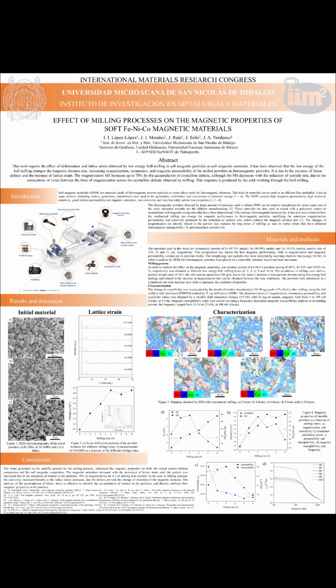Regarding the materials and methods, we used commercial powders of iron, nickel, and cobalt with high purity and particle sizes around 130, 10, and 12 micrometers respectively. This composition has shown the best magnetic performance, both in magnetization and magnetic permeability, in previous works. The morphology and particle size were analyzed by scanning electron microscope. In order to analyze by SEM, the ferromagnetic powders were placed on a removable substrate to prevent the movement of the particles.